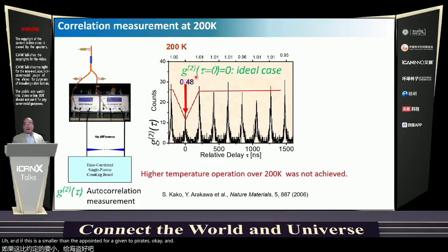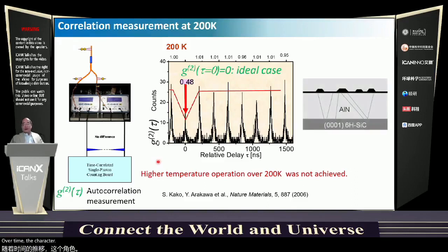And at 200 Kelvin, we succeeded in observing g2(0) below 0.5. So we were very happy to realize the highest temperature at the time for single photon emitters based on semiconductor quantum dot structures. However, this was done in 2006, and we could not realize temperatures higher than 200 Kelvin. This is probably mainly due to some kind of dislocation effect near the existing quantum dot structure.